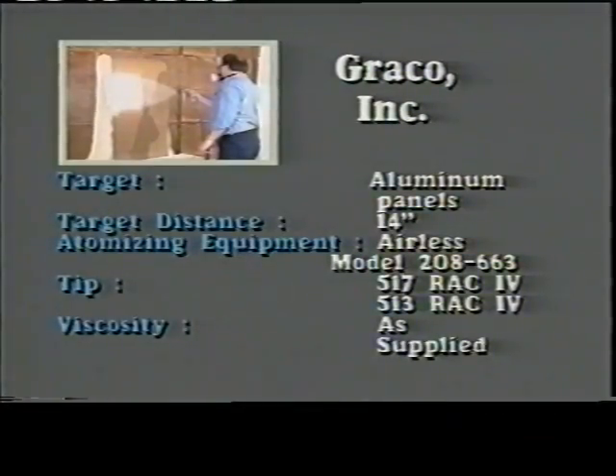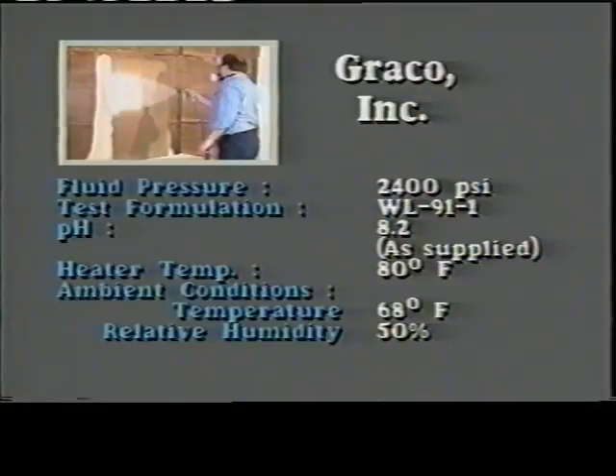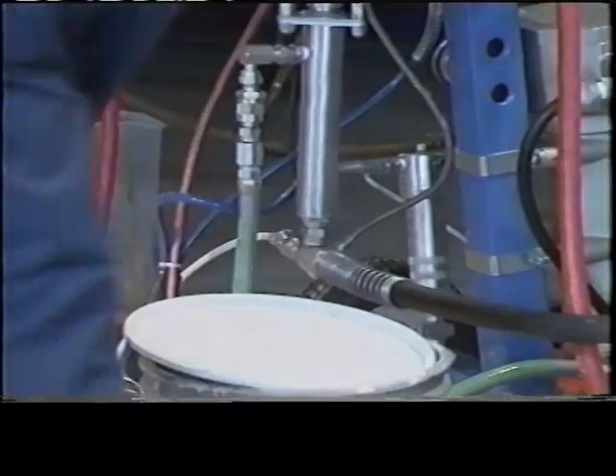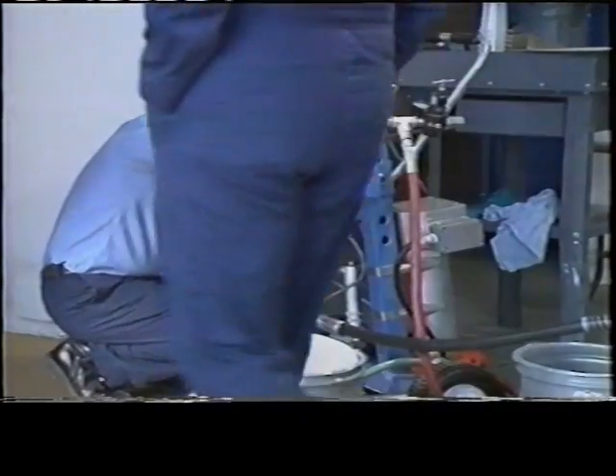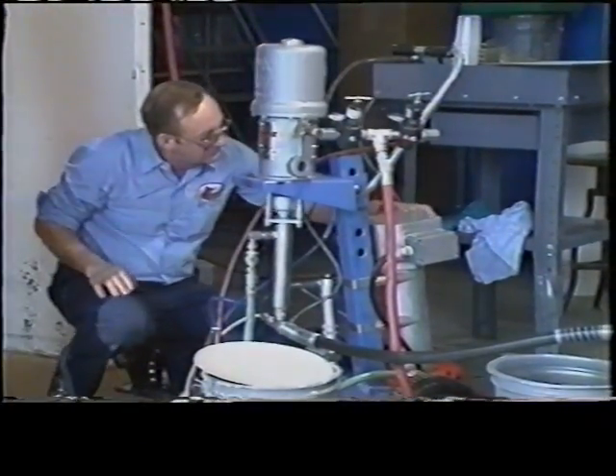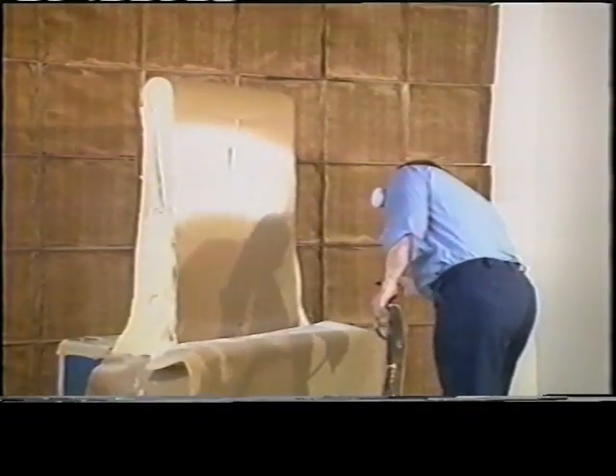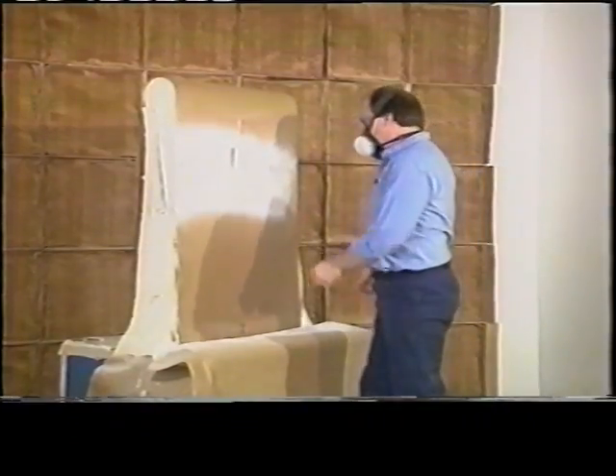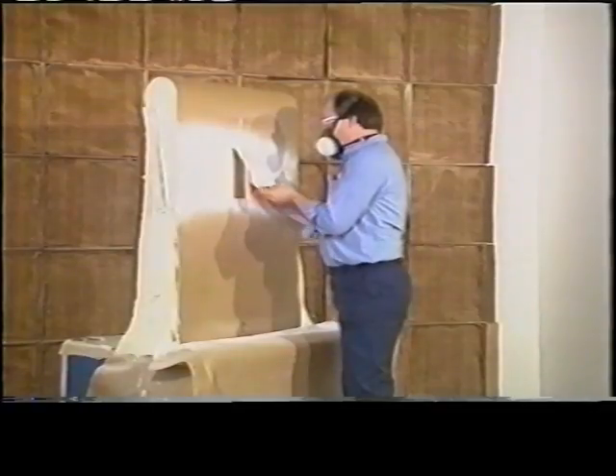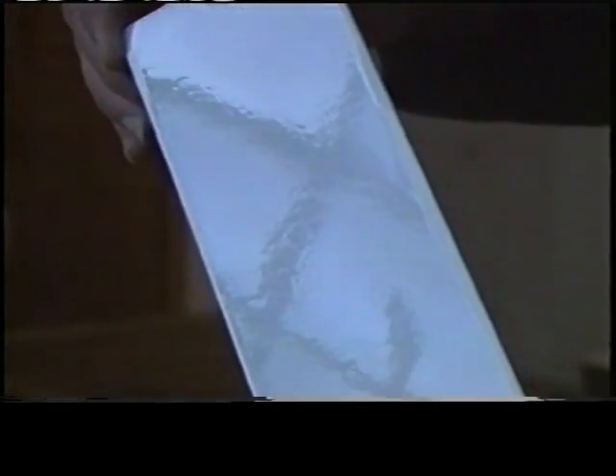Although Graco Incorporated ran trials on both airless spray and air-assisted airless spray units, the airless spray unit was the primary focus of Graco's testing. Graco, the 4th manufacturer in our study, chose to test an airless spray gun. This unit did not require any reduction in the test formulation's viscosity, but the coating was heated to a temperature of 80 degrees Fahrenheit to improve application. The heated coating went on very smoothly. Flow and leveling were excellent, as the uniformity and high gloss of the dried coating demonstrate.